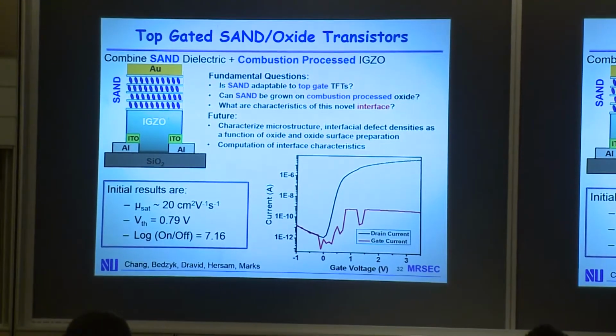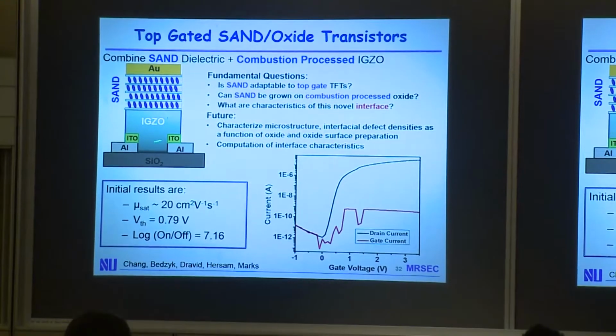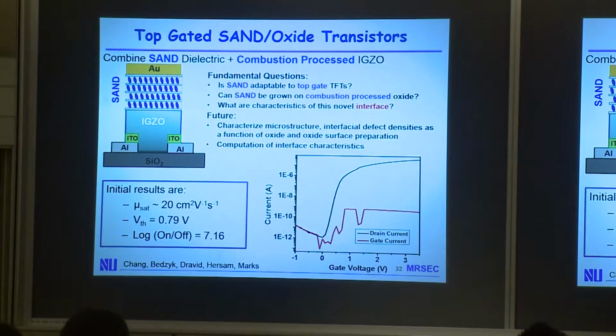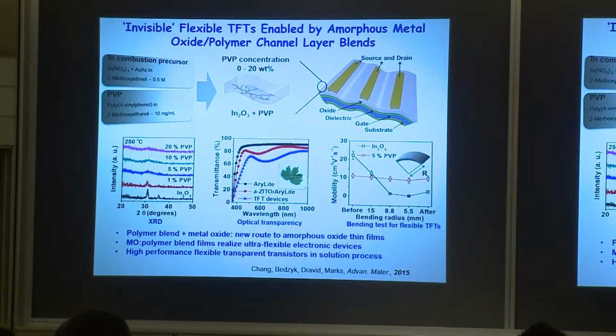You might say, hey, I really want to have bottom contact type devices. So in fact, you can grow sand on top of IGZO. You can put IGZO on the patterned source and drains, a whole array of them, and then the sand grows right on anything that has a hydroxylated surface. So you can grow the sand and then put on the gold contact. Works very, very well.